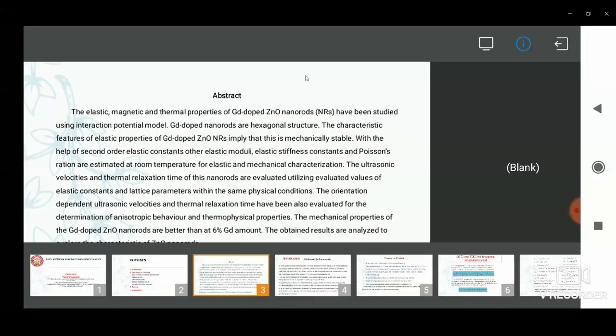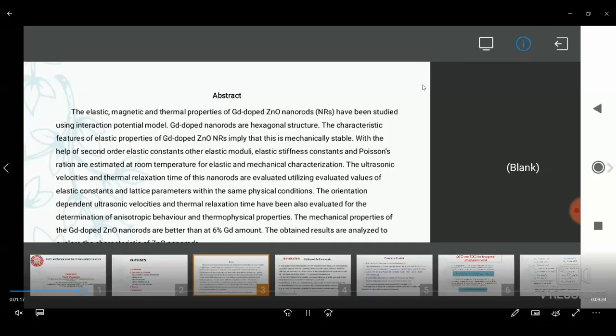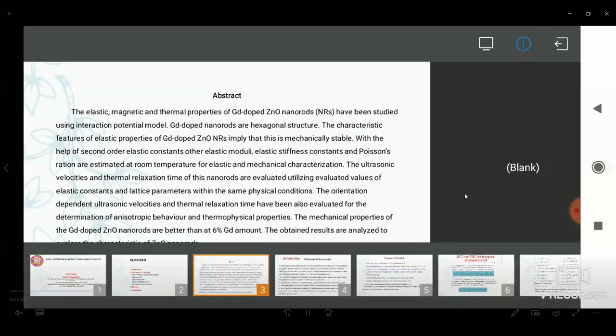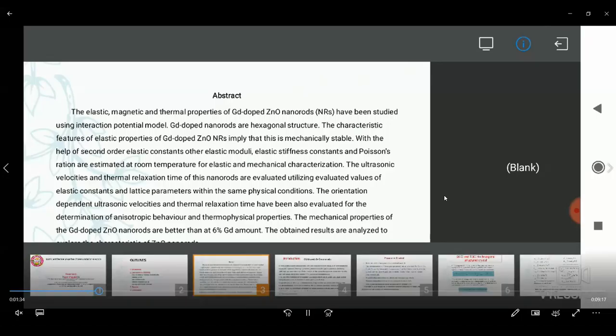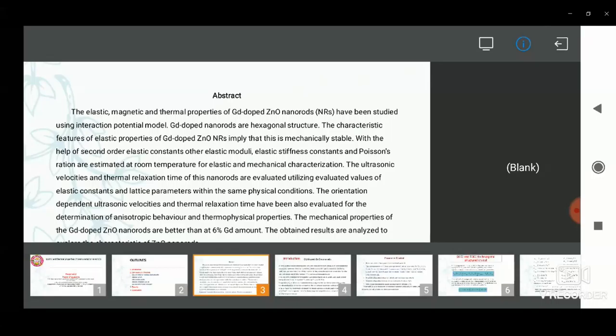The characteristic feature of the elastic properties of the Gd-doped zinc oxide nanorods is that they are mechanically stable. With the help of the second order elastic constants, the elastic modulus, elastic stiffness constants, and Poisson's ratio are estimated at room temperature. For the elastic and mechanical characterization, the ultrasonic velocity and thermal relaxation time of the nanorods are evaluated. The elastic constants and the lattice parameter, the physical constants, the orientation dependence, the ultrasonic velocity and the thermal relaxation time have also been evaluated to determine the anisotropic behavior of the thermophysical properties.